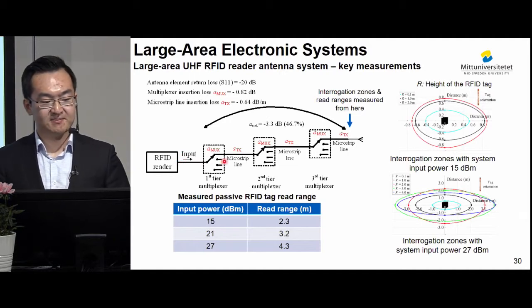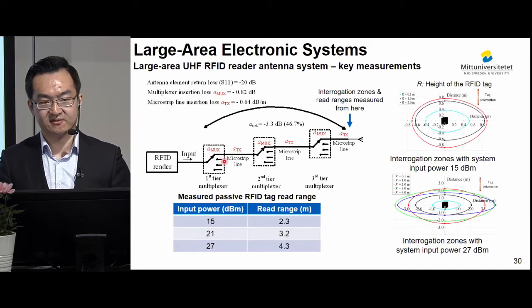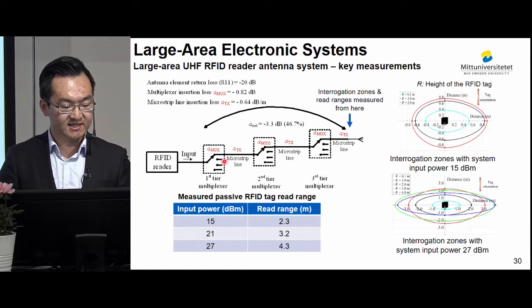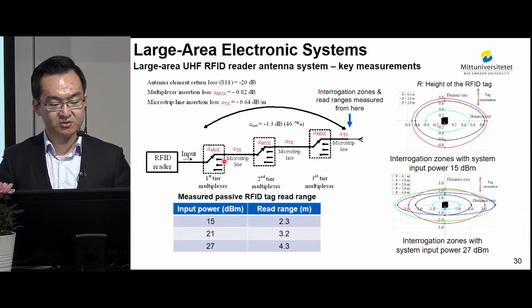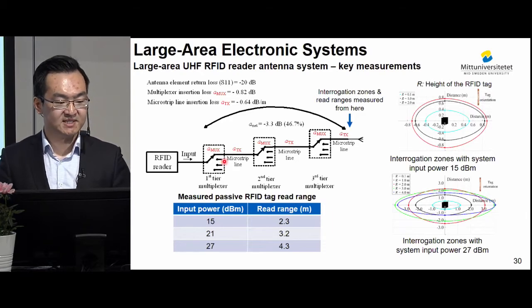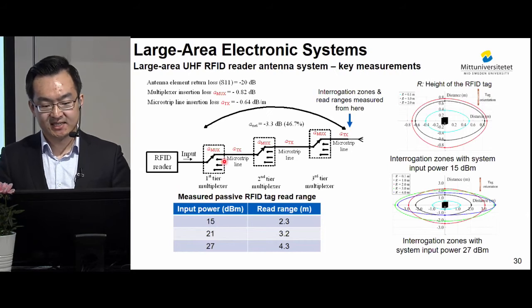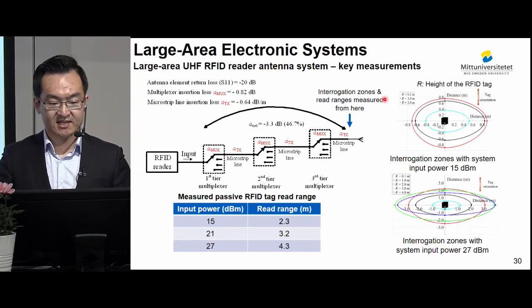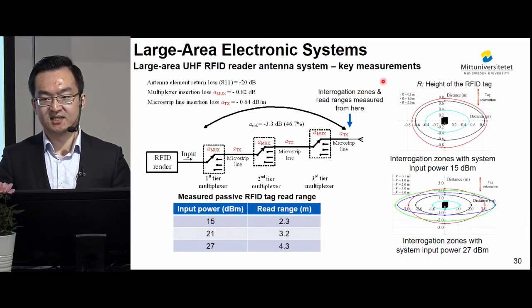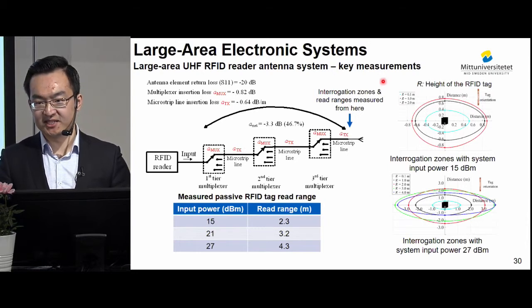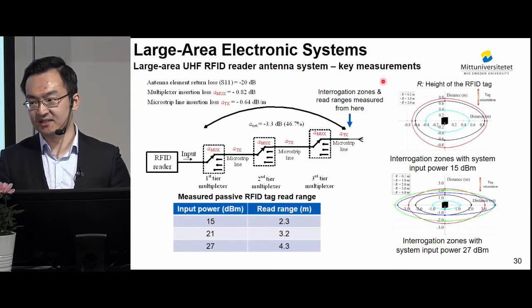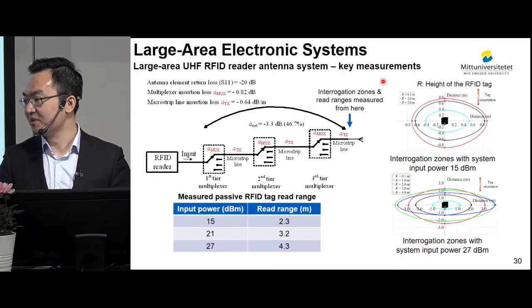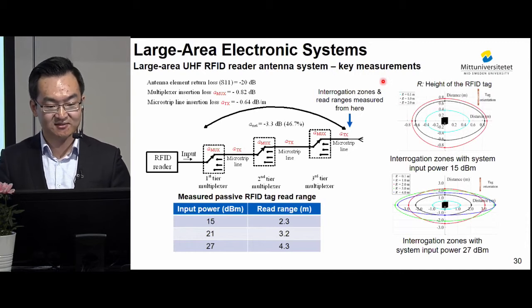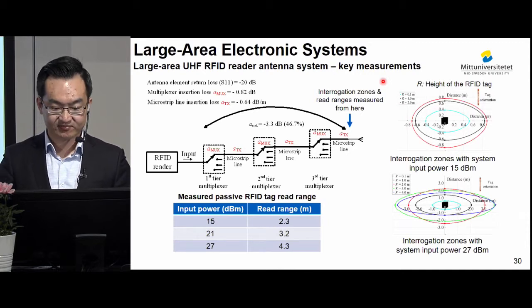And we measured the passive RFID tag read range of this antenna system. It showed that we have a read range between 2.3 meters and 4.3 meters with input power from 15 dBm to 27 dBm. And we also measured the RFID tag interrogation zones. It can be seen that the conclusion is similar to the HF RFID reader, that the interrogation zones can be controlled with input power and the heights of the RFID tags.